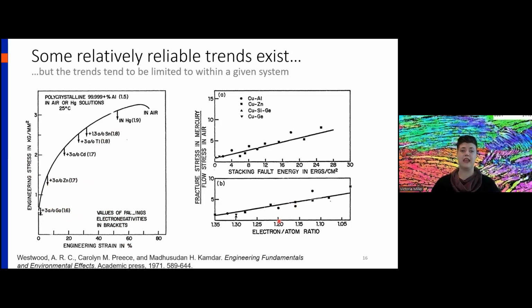Over here, you can look at the electron per atom ratio, and you can look at the stacking fault energy, and you can say, okay, when we look at the fracture stress in mercury normalized by the fracture stress in air, divided by the flow stress in air, you can see distinct trends that emerge here. However, all of these trends tend to be sort of limited to within a single system.